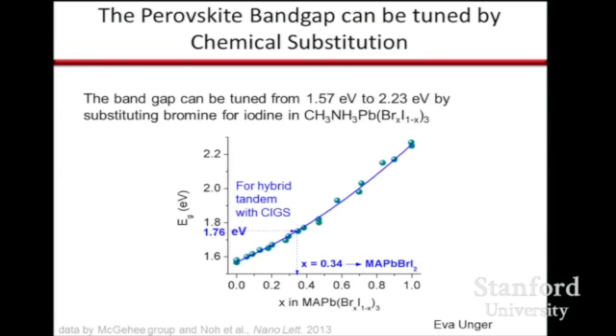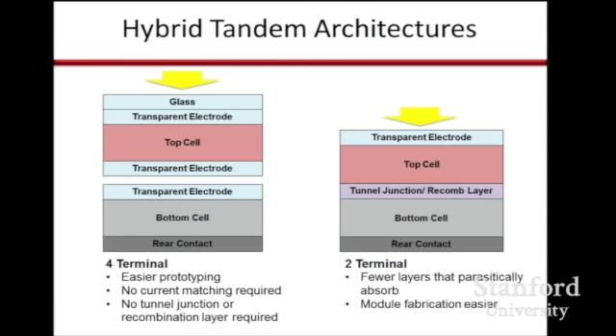So my group wants to make tandems, and for that we need about a 1.8 electron volt band gap. And Eva Unger, in collaboration with Hema Karunadasa's group, has varied the halogen content. By putting in bromine, we can gradually tune the band gap and get pretty much whatever band gap we want for a tandem solar cell. So then we've gone on and started making the tandems.